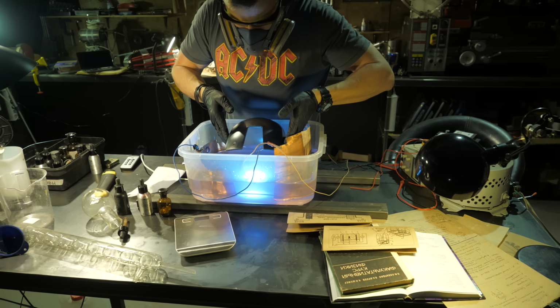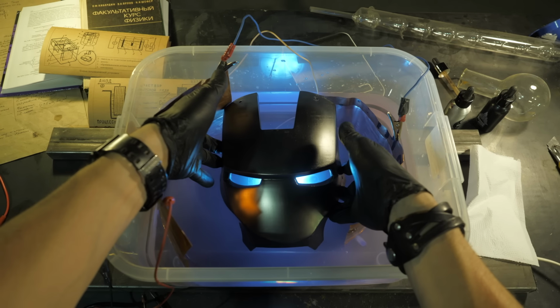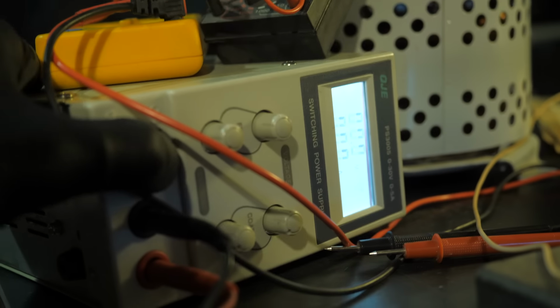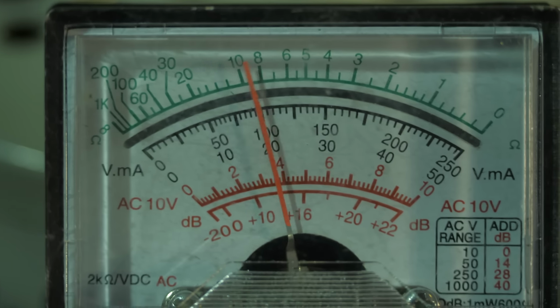Immerse in the bath a solution of copper sulfate, a drop of sulfuric acid and some other filth, the donor copper plates, and the mask itself. Plug the plates to a positive and the mask to a negative wire. Supply current and begin long experiments with current density and its effect on coating quality.